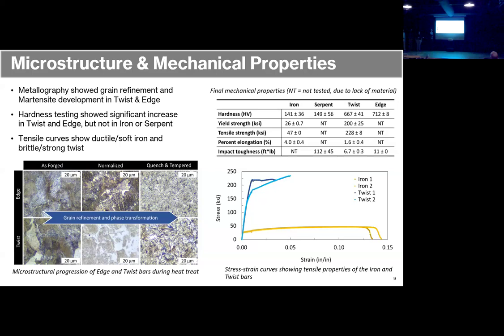So we did hardness testing, tensile testing, and impact toughness testing. Hardness is you just make an indent in the material and then see how far that goes, and you can test the hardness like that. So you can see with our iron and serpent, those ones that we smelted, they're very soft compared to the commercial steels. We went from about 100 Vickers to 700 Vickers. And then 700 Vickers, that's stronger than most knives would be. 100 is closer to like a structural steel that needs to be tougher.